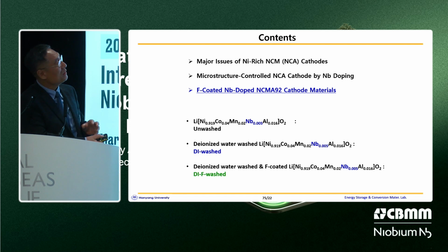And let me introduce the fluorine-coated niobium-doped NCMA cathode materials. We optimized the niobium-doped cathode material composition like this one, with a niobium doping amount of 0.5 mol%. The optimized cathode is denoted as the unwashed cathode. Then we treated it with deionized water washing, called the DI washed cathode. The third cathode material, the deionized water washed and fluorine-coated niobium-doped NCMA cathode, is denoted as the DIF washed cathode.